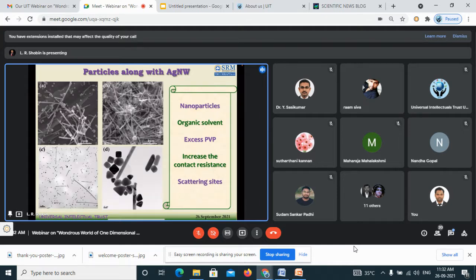Okay, here comes the real problem. You got wires, but still it has particles along with it. So in the solution process, if you are looking for growth of wire, you cannot avoid the growth of the particle, because the wires are all growing from these particles, right? So you cannot avoid them basically. Producing particles along with the nanowire will obviously happen. You cannot avoid it. So what you can do is remove them.